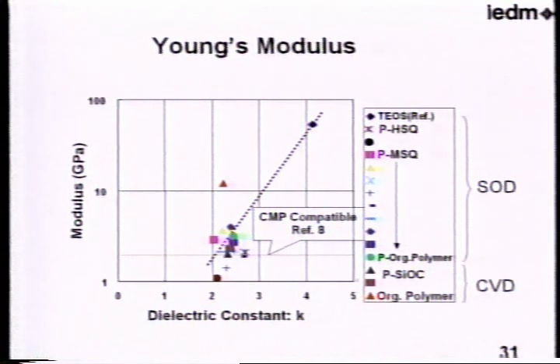This figure shows the modulus as a function of dielectric constant K. As you can see in this figure, for the Low-K film, especially porous Low-K film with the K value less than 2.5, the modulus is about 1/10 compared with the reference SiO2 film. So in that case, the porous Low-K material is very, very weak in the mechanical strength as compared with SiO2. Note that this point is non-porous material of organic polymer, like polyethylene-based polymer CVD. In that case, the mechanical strength is as high, above 10 gigapascal.